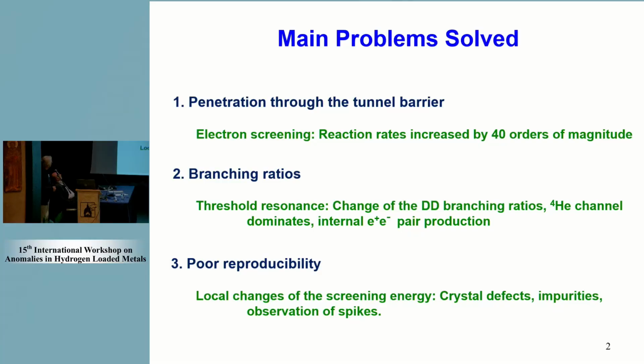So coming to the beginning of my talk, I would like to show you that some problems in DD cold fusion we could resolve; we could find a solution based on these results. And I would like to present how we can do it. The main point was penetration through the Coulomb barrier, and the solution will be electron screening. Another point is that the branching ratio at very low energies, at thermal energies, seems to be completely different, that the helium channel dominates, and there are many experimental indications for that.